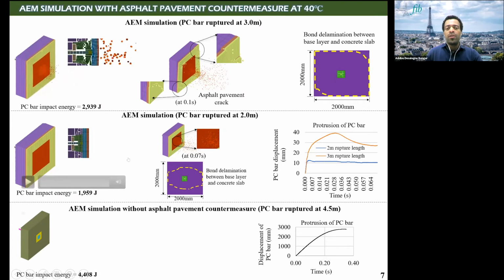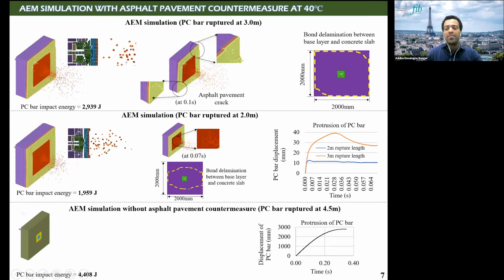So we also carried out a similar simulation by rupturing the PC bar at 2 meters. This time the impact energy is around 2,000 Joule. This time almost no severe damage, just a thin layer of cover layer asphalt pavement was spalled down. This one is the PC bar displacement versus time. When the bar rupture length is 2 meters, the impact energy is too small, and the protrusion is also small. Whenever you increase the rupture distance, it means you are increasing the strain energy and more impact, more damage